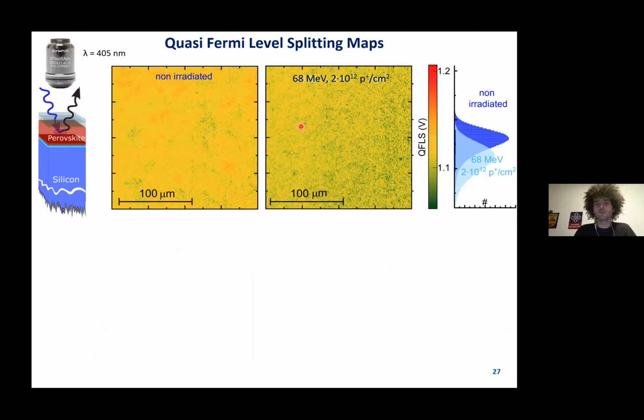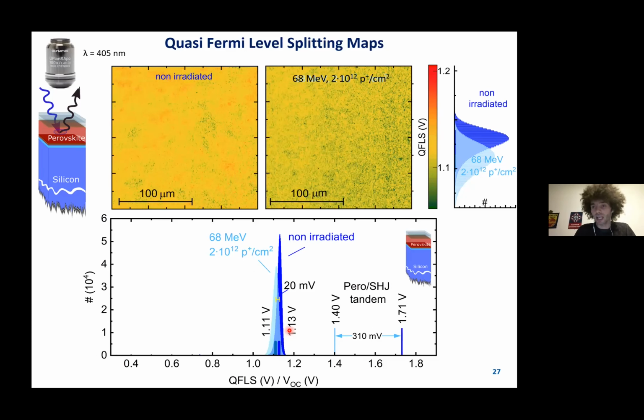And as you can see here, there's a slight reduction in quasi-Fermi level splitting in the perovskite, but it's not much, right? It's about 20 millivolts drop here, while the tandem undergoes a very strong decrease in VOC. So this damage is not because of the perovskite, but it must be because of the silicon. And we've irradiated silicon single junctions as well. And we see this massive drop in VOC here. And we also see a reduction in PL of the silicon and a reduction in the lifetime of the silicon substrate. So we think we understand the perovskite silicon tandem device, and it's not good to use it in space.